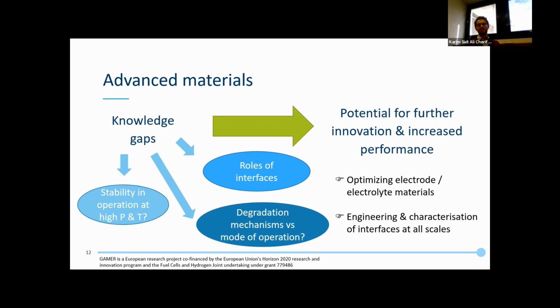And my last question: here you talk about the interfaces, electrolytes and electrode materials. What about the sealants? Yes, we are lucky to have a partner, CoorsTek Membrane Science. We have developed a proprietary sealing technology. We use a tubular configuration, so we have much less sealing interface than we would have in a planar one. It's just on the bottom of the part, in the colder area. We have not seen any issue yet with this sealing technology, and that has not been a showstopper here. Of course, we have to put ourselves in the perspective of 40,000 hours. I have no data on that so far, but at this very moment, this is not a showstopper.